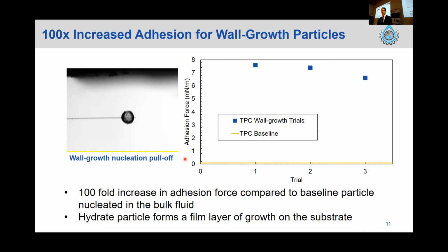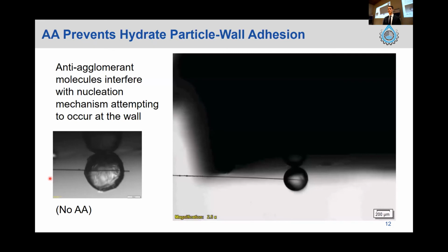So for each of these, you can see that it's generally within the region of 6.5 to 8 millinewtons per meter, which is actually a 100-fold increase from the baseline and roughly the time variant trials. So that obviously poses a much larger risk in the context of plugging. And that, as I mentioned, was basically as a result of that film layer really increasing that adhesion through a chemical interaction. So the next step for this was to introduce anti-agglomerants and look at how they might affect that adhesion force.